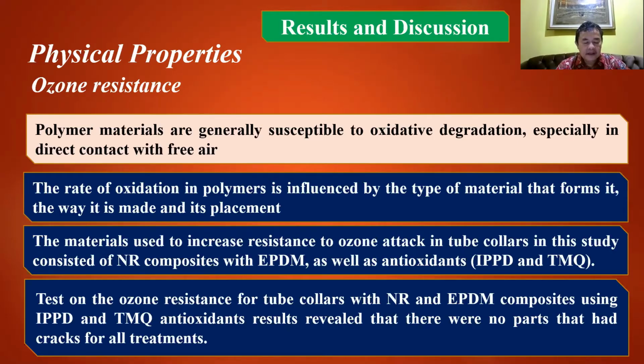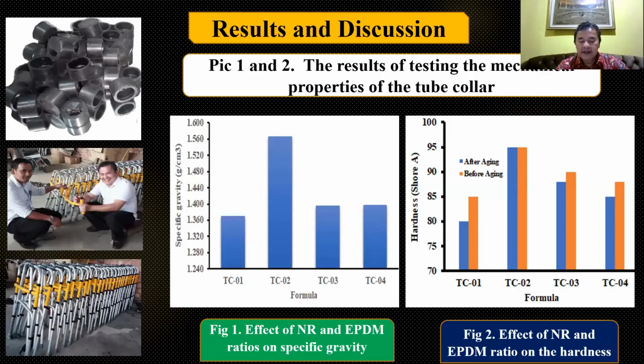Figure 1, effect of NR-EPDM ratio on specific gravity. The result of specific gravity test of the four formulas. Figure 1 shows the specific gravity value of the TC02 formula is higher than the other formulas. This illustrates that the density of the forming material in the TC02 formula is denser per unit cubic centimeter than the other formulas.